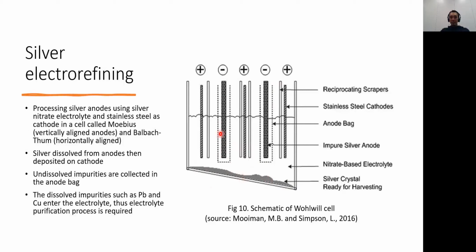It happens because silver is not solidly deposited onto the cathode. For copper, if you guys have visited a copper smelter, the deposition of copper on the cathode is like solid deposition. So the copper will stay there and be cathodically protected from the process. Gold also behaves the same. Gold will be solidly deposited on the cathode surface, but silver is different. The deposition of silver is not solid deposition, but it's a dendritic deposition.